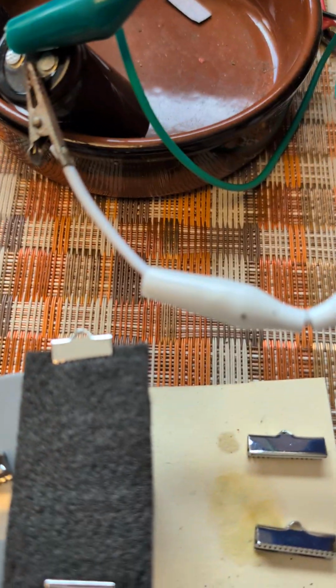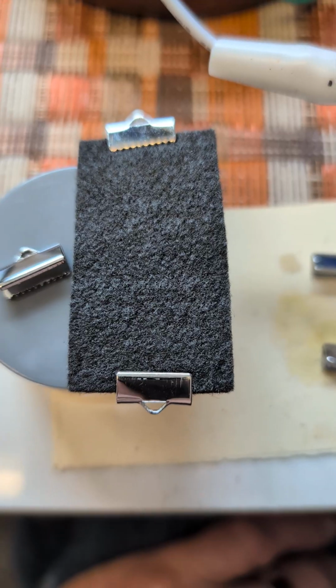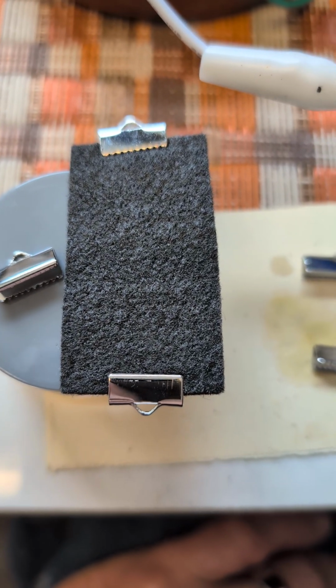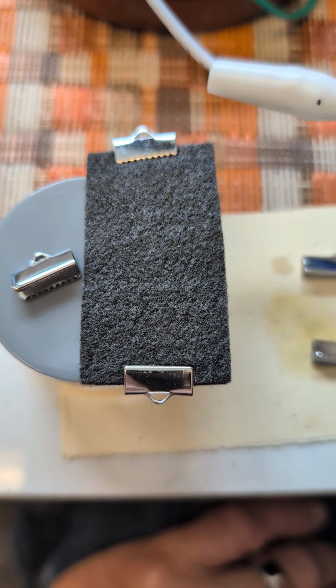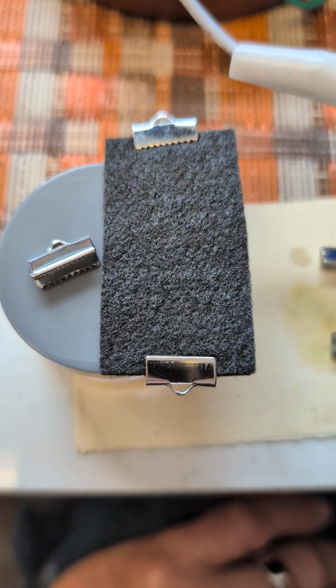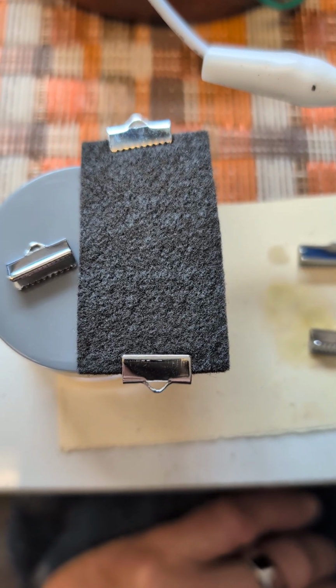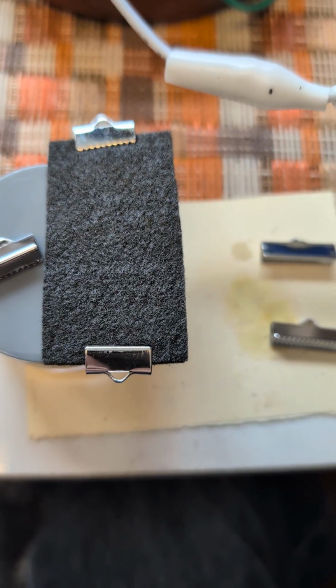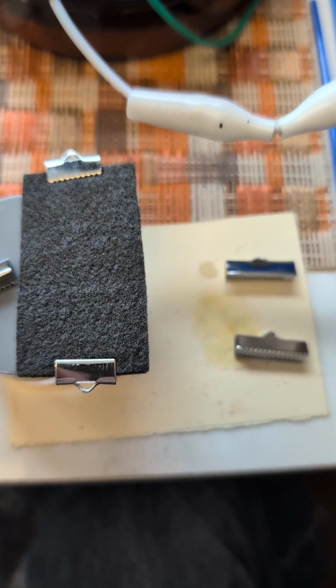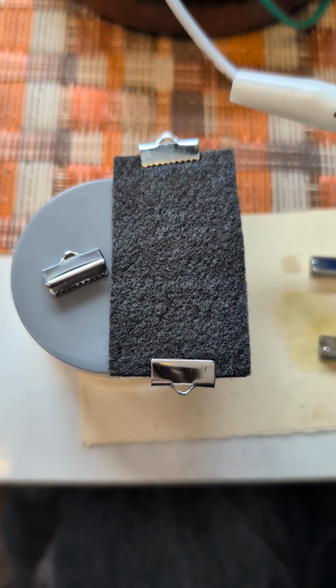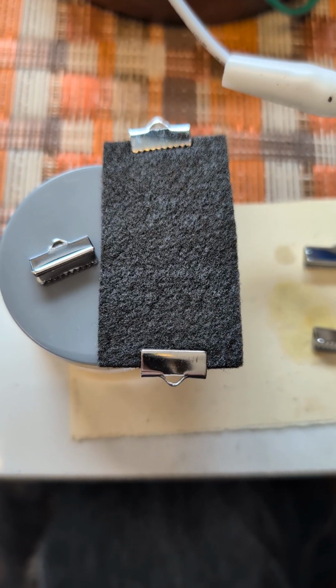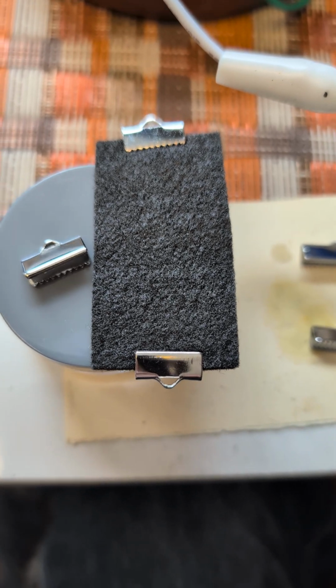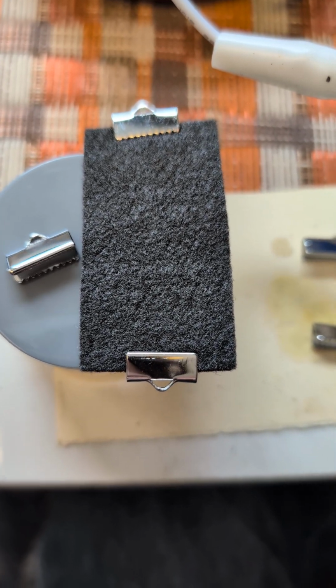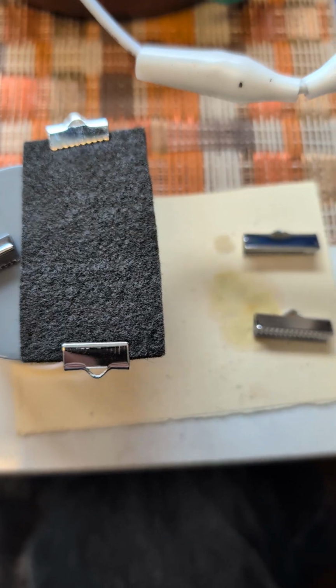But what we will do is thoroughly clean with 95% ethanol and dry, and nickel plate. We do light nickel electroplating for about 20 minutes at a certain voltage. My student has that all in the notebook. And we will examine the graphite that's modified by scanning electron microscope. But it makes a difference. If you put too much nickel plate, you're going to lose your flexibility of the graphite felt. See, that's what the application of it, it's flexible.